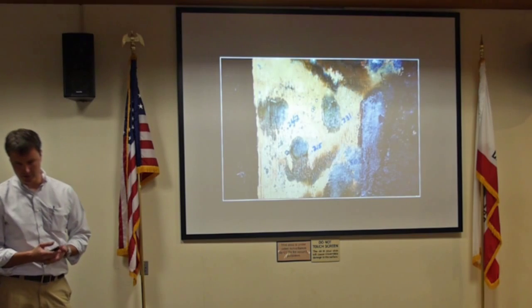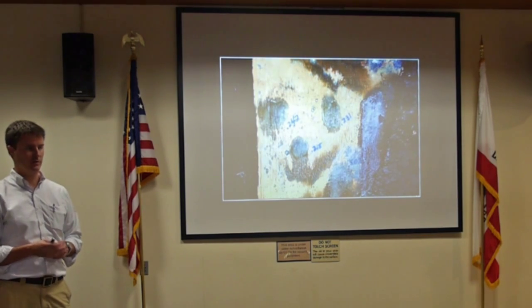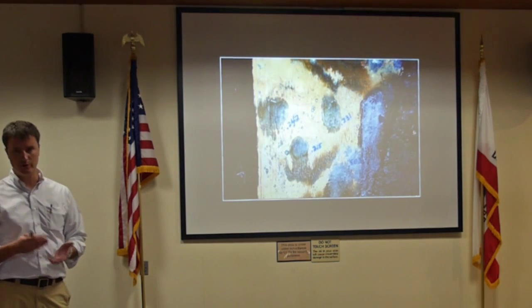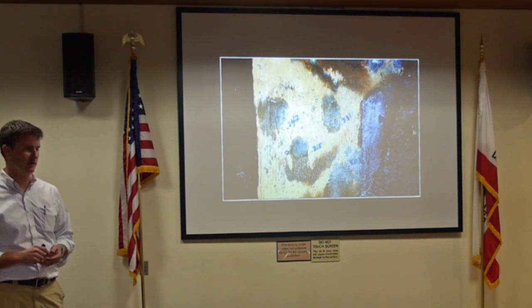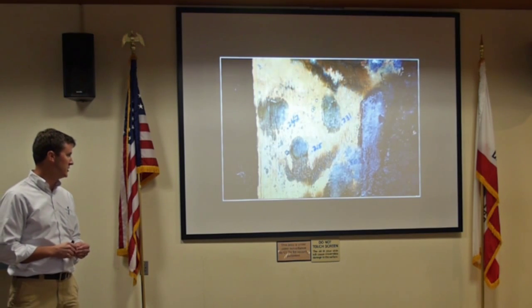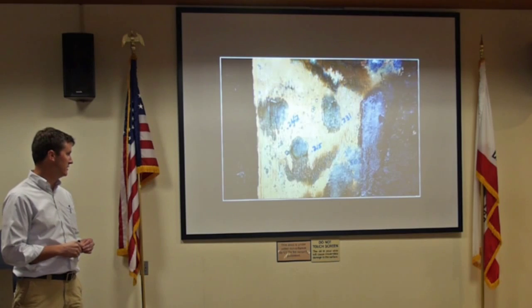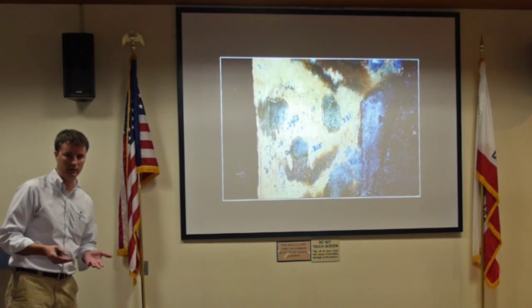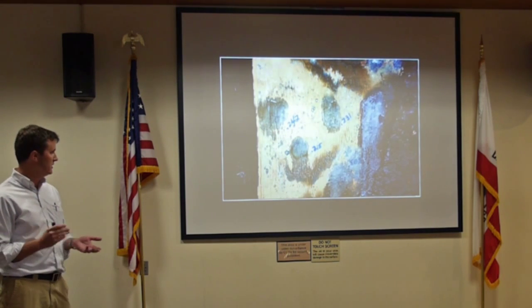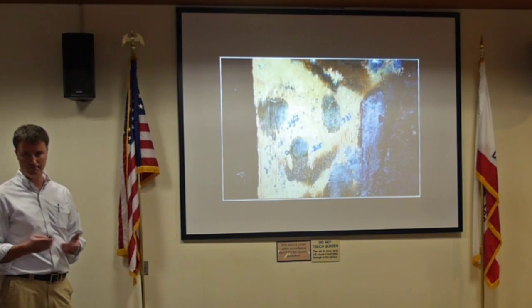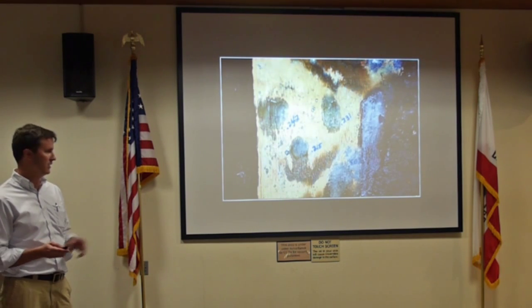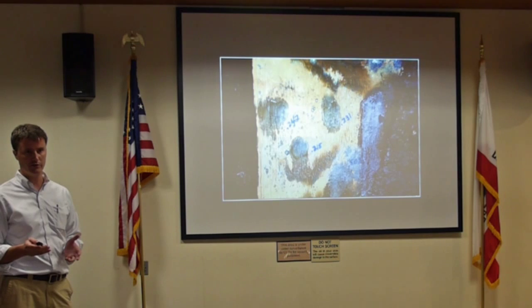So as part of the investigation, we went through and looked at where you started and where you ended up. Using ultrasonic thickness measurements, this flange actually started about ½ inch thick. You can see just based on these readings, after over 35 to 40 years, it ended up losing basically half of the thickness. This was not an area that had failed, so this is also a concern.